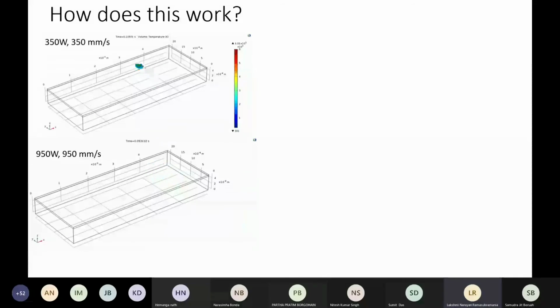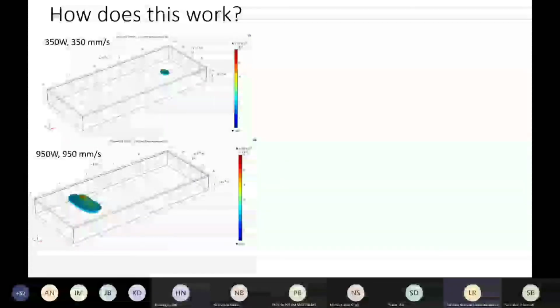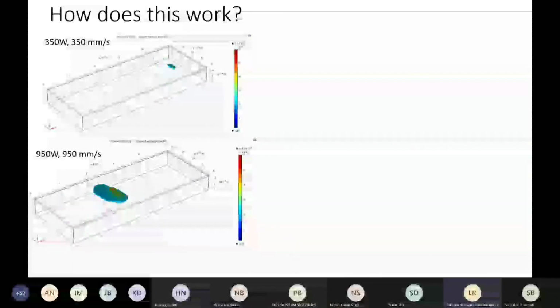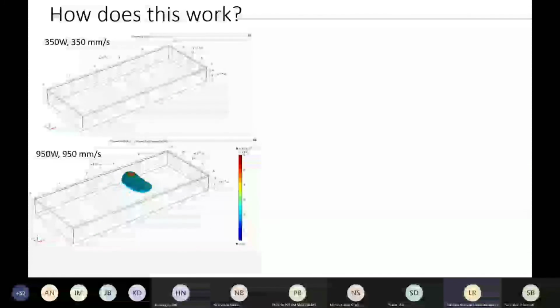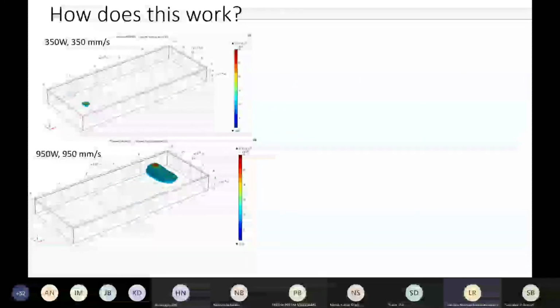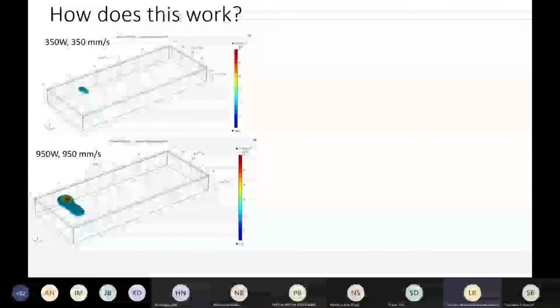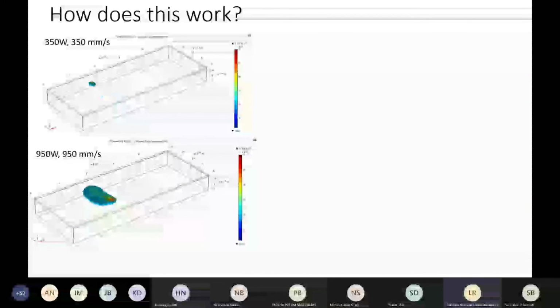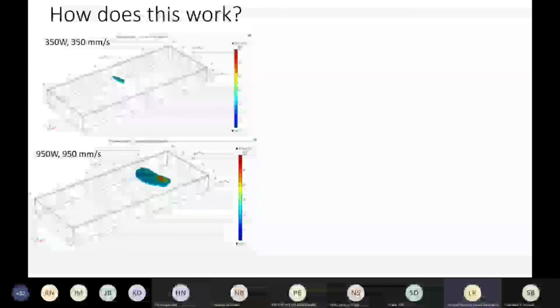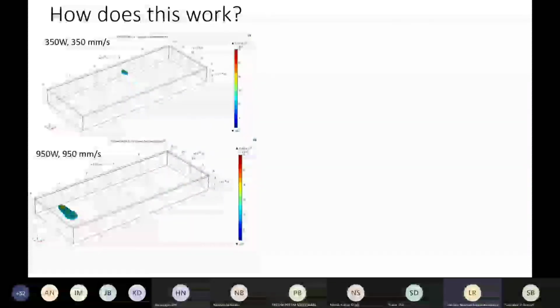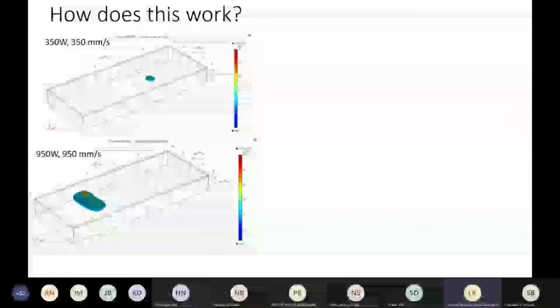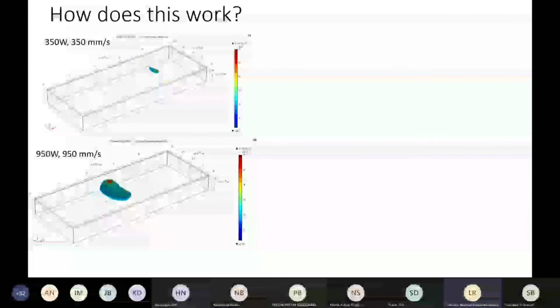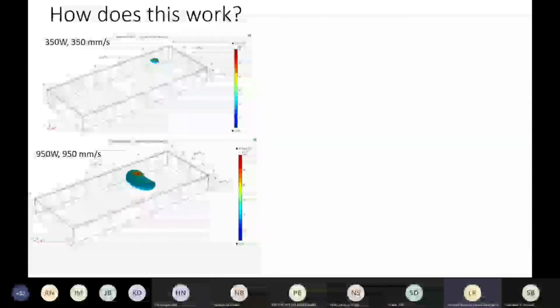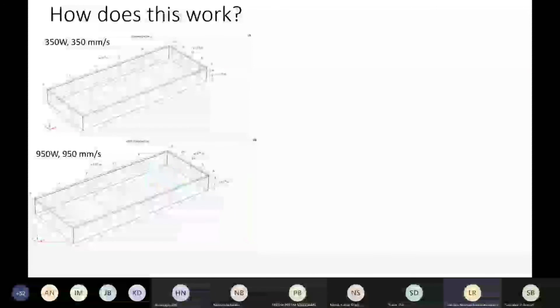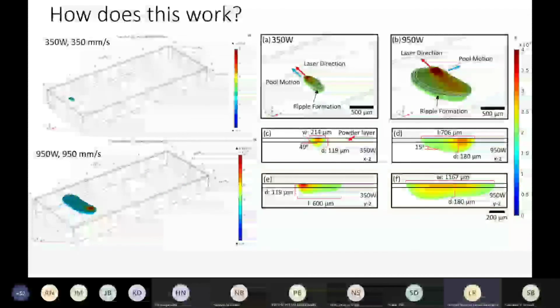Now what we do is we'll go for the stripe scanning strategy. In the stripe scanning strategy, what we have done here is we have used high power and high speed. With the use of high power and high speed, the melt pool remains molten for a longer period of time, as in the heat is retained for a longer period of time. And because of the higher speed, the return of the laser is so rapid that the melt pool appears to be larger, or rather a larger volume of material has been melted, which allows solidification to take place slowly.